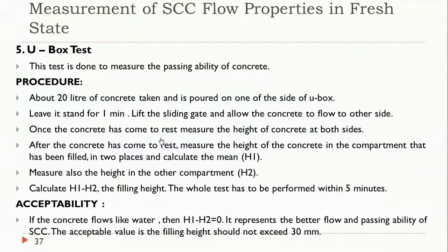So the difference h1 minus h2 gives the filling height of the self-compacting concrete. This test has to be completed within 5 minutes. If the concrete flows like water, then both compartments will have the same height, and h1 minus h2 will be equal to 0. The acceptable limit is that the height difference should not exceed 30 mm.